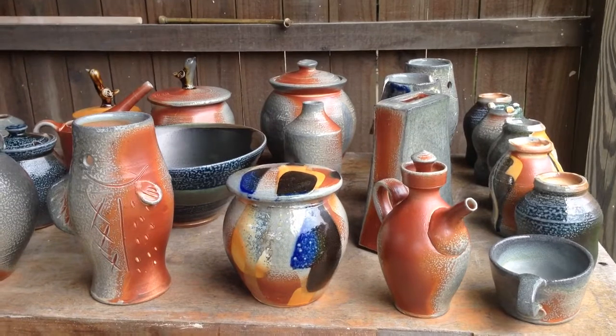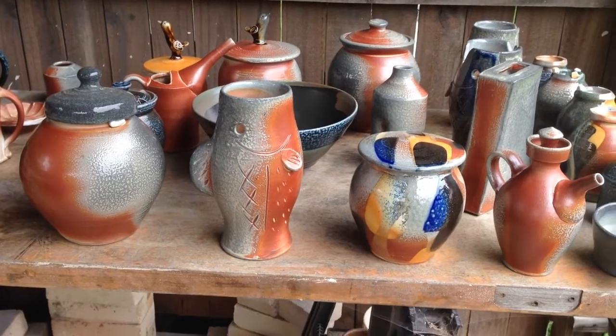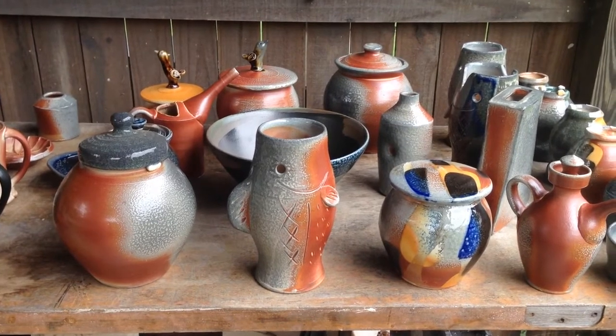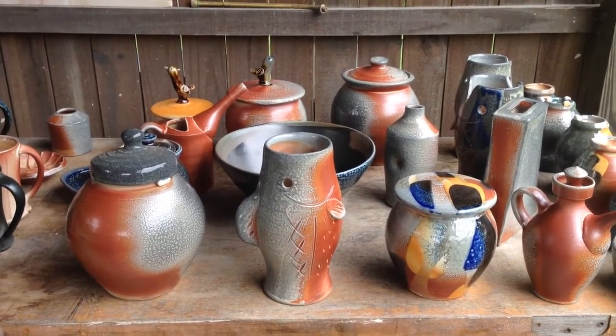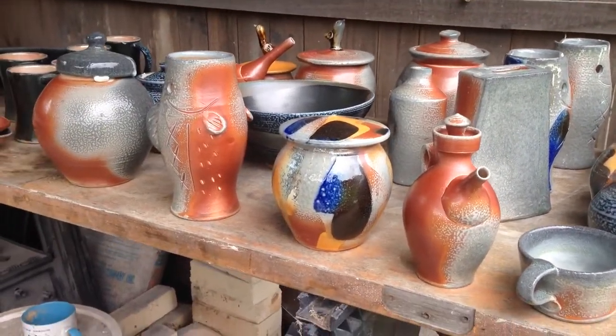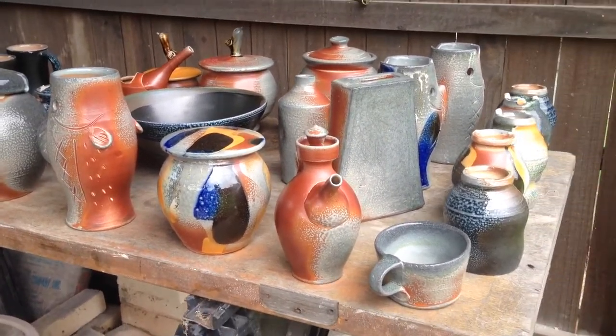Hey folks, I'm going to show the pots that came out of the firing I just did. If you've been following along on Facebook or Instagram, you know this was a firing where I introduced the soda in a different way. Instead of spraying, I used a variation on the Gale Nichols method where I mixed soda ash, baking soda, and whiting together, then added that to wood chips and dumped that combination into the firebox on a piece of angle iron.